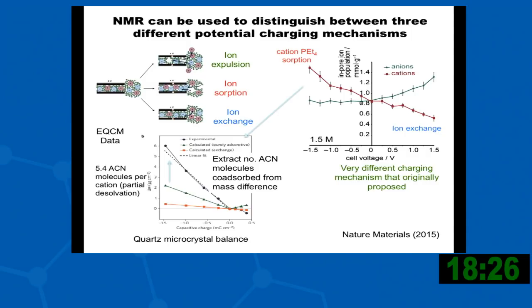And so this is a plot where we're charging positively, and we're looking at the cations and the anions. And what you can see, interestingly enough, when you charge to positive voltage is you get an ion exchange mechanism. The positive ions come out, the negative ions go in. But interestingly, when you charge to negative potentials, the anion concentrations stay about the same, and all you get is cation adsorption. So there are 2 mechanisms that go on in these systems. And then, and this is now in collaboration with Patrice Simon's group, using electrochemical quartz crystal microbalance measurements, we can measure the mass changes on charging, and what we can then do is calculate how many ions go in and how many solvent molecules go in at the same time, and we were able to show that you only get partial desolvation of these molecules.